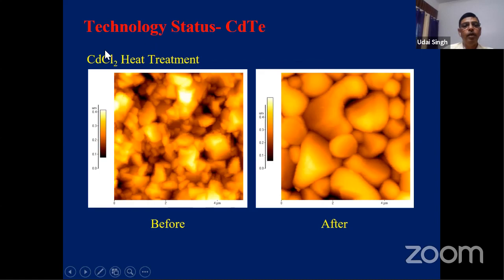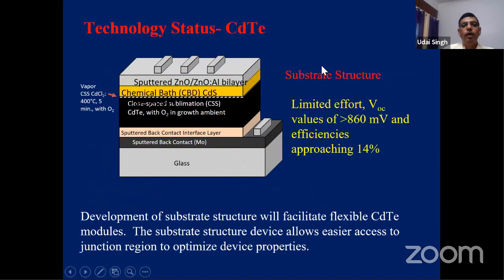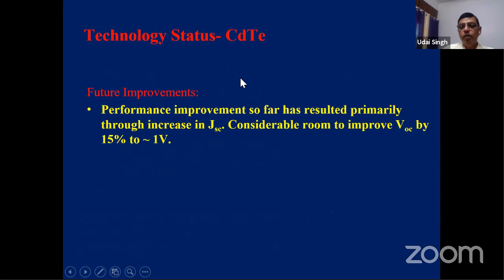But people found that when you treat with cadmium chloride, you get very large grains. That was the achievement in the 80s. Now this is the common process used. We can also have a substrate structure. Further improvement is still needed, as cadmium chloride treatment has not reached the maximum efficiency.